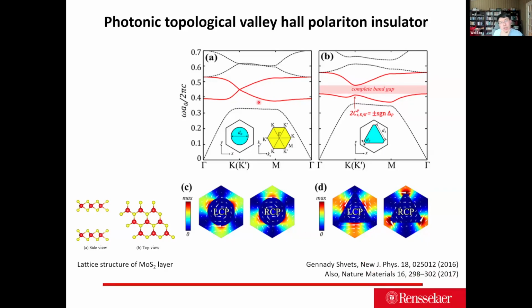Essentially, the valley Hall design is a photonic graphene. So you have C6 symmetry, with holes etched in the lattice. You start with a photonic graphene, and then you break the symmetry and make one atom become larger than the other, photonic atom. So now you have a MoS2-like crystal. One atom is bigger, the other atom is smaller. So now you have the photonic valley.